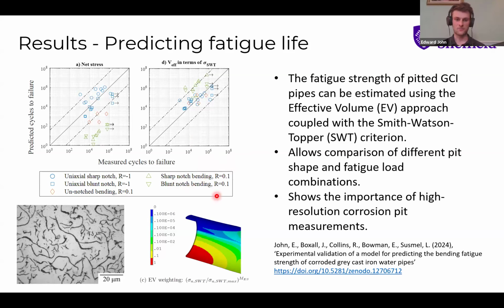So just as an interesting side, the effective volume approach is basically looking at how much of the pipe volume experiences the highest stresses and uses a ratio of that to figure out what loading conditions are most damaging. So although this is an empirical approach, it's probably linked to the fact that we have all of these inclusions in the cast iron pipe material that act as the initiation points of failures. So if we expose more pipe material to high stresses, we're more likely to find a worse graphite flake, basically, that can cause the failure to initiate. But basically, in summary, using these models together allow you to predict how damaging a particular combination of pit shape and loading will be in a cast iron pipe.